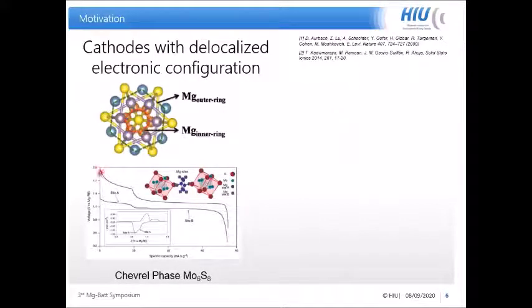If we look at the structure, the purple bars represent the molybdenum atoms, and we see that 6 atoms form a hexagonal ring, and they share 4 electrons transferred during magnesium insertion. So on average, each atom only takes about 2/3 of an electron. That's why in battery performance, it shows very long-term cycling.